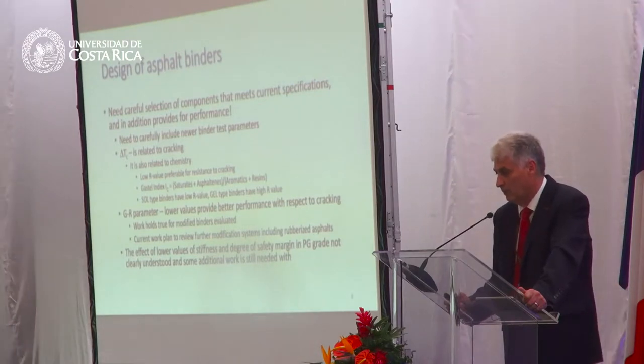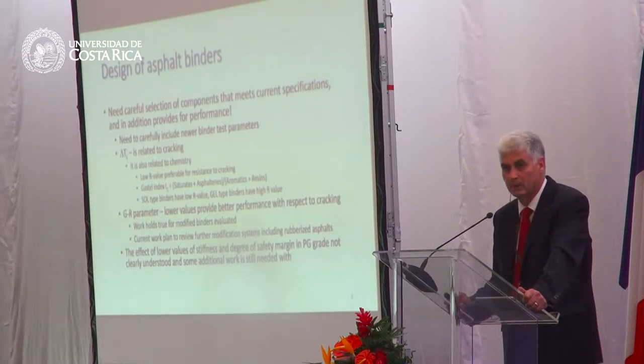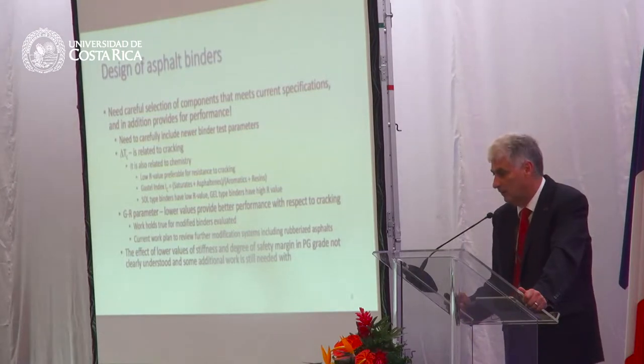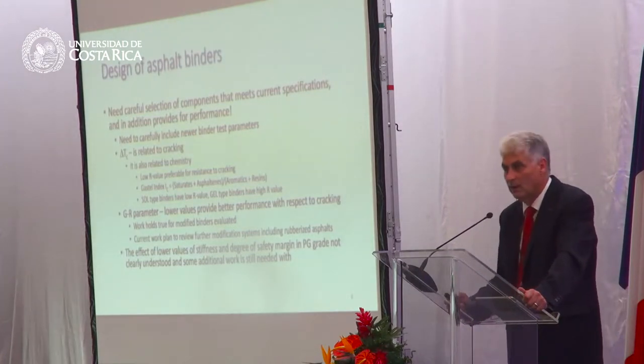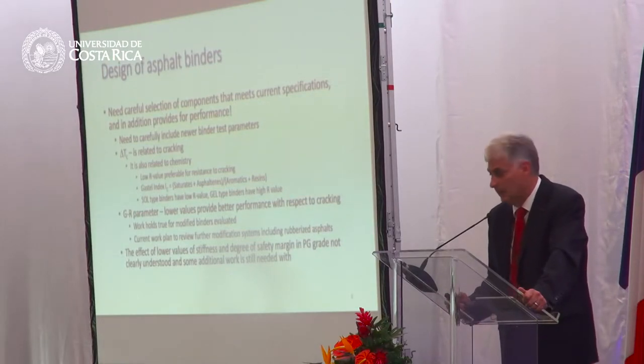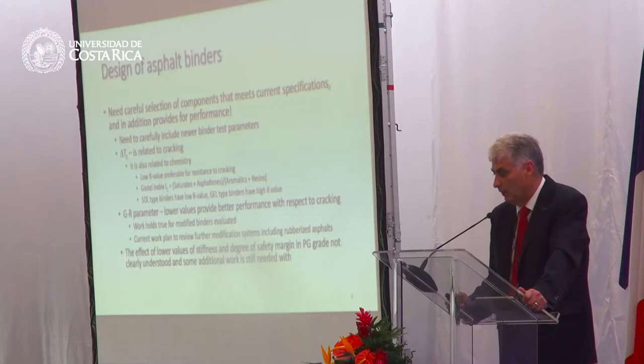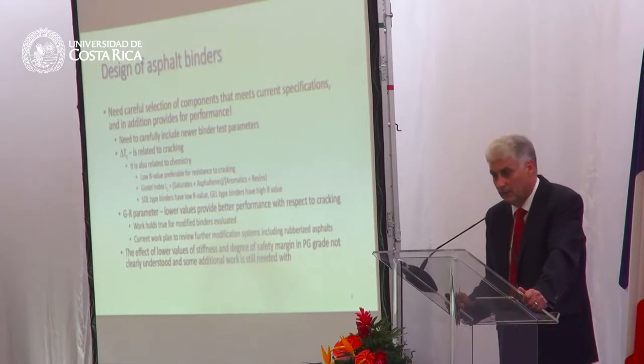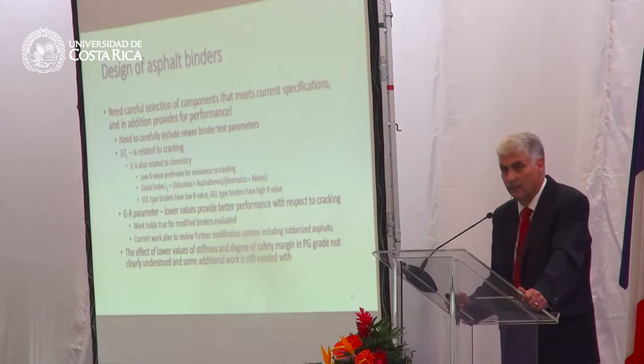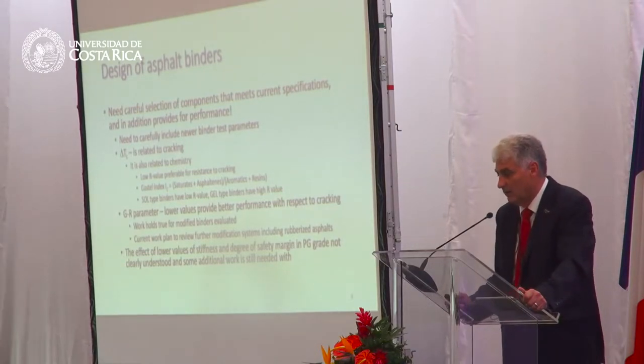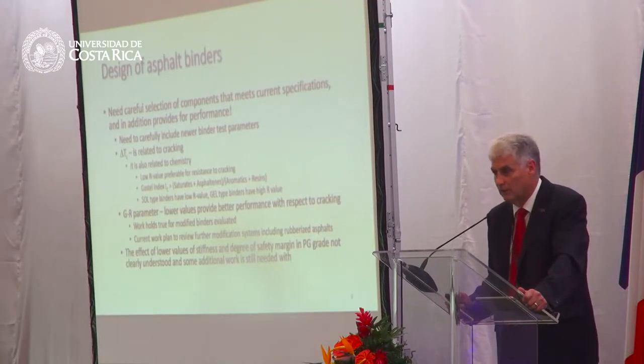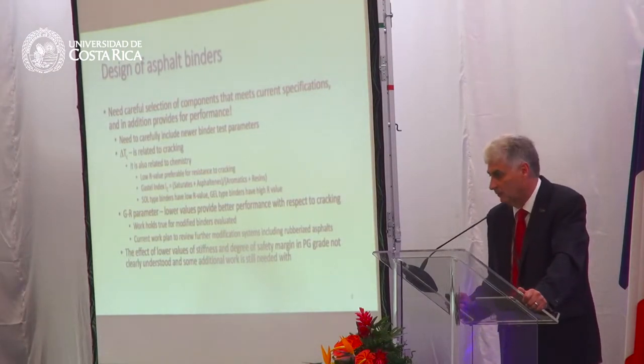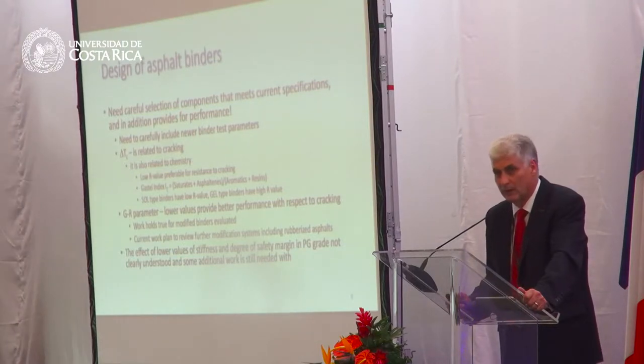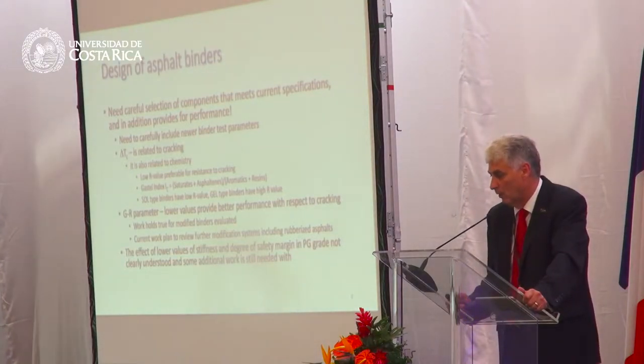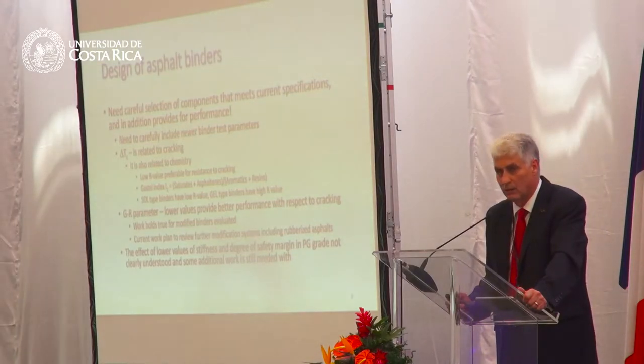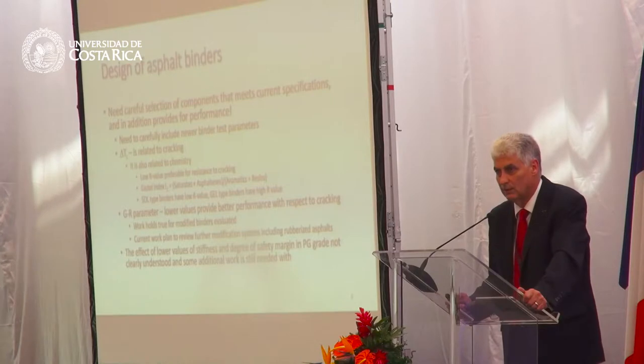And there's a few of these that we need to look at, a few things that have been developed recently. There's a parameter which is called delta TC, and I'll explain what this is in a few minutes. It's related to cracking. It's also related to the chemistry. The low R value, which is a rheological index, is preferable for resistance to cracking. We can use things like the Gaestel index, that's related to the saturates and the asphaltene content divided by the aromatics and the resins. We know that the sol binders have the low R values and the gel binders have the high R value. And all of these things can be tied to the delta TC.